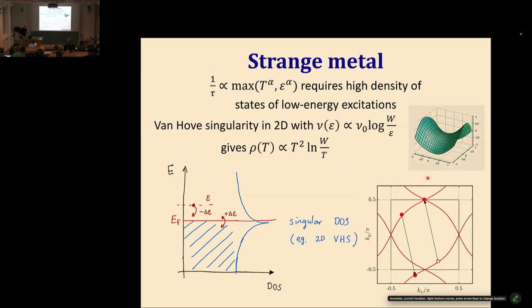Actually, maybe following up on what Alberto asked, this T squared log T, does that include the umklapp scattering, or is it just plugging in the single-particle rate? Yeah, no. To really see this in the resistivity, you must have umklapp scattering. By the way, the scattering process that I illustrated here is an umklapp process. But this comes from processes that may be umklapp or non-umklapp. There must be umklapp somewhere. But the important thing is that it comes from two-electron scattering processes where one of the four states involved, either initial or final states, is right at the Van Hove singularity.